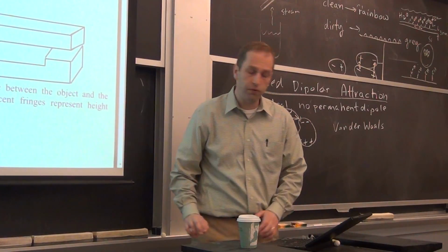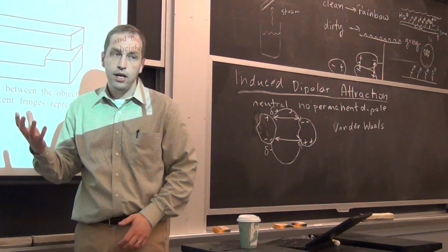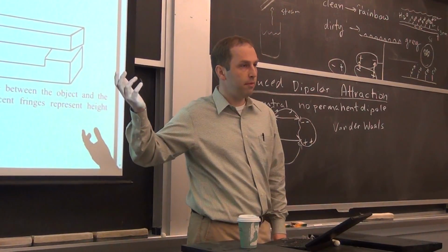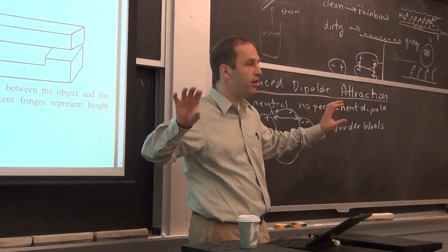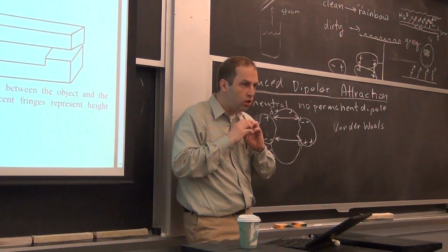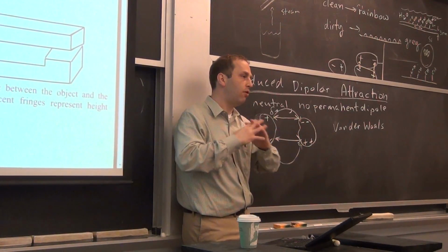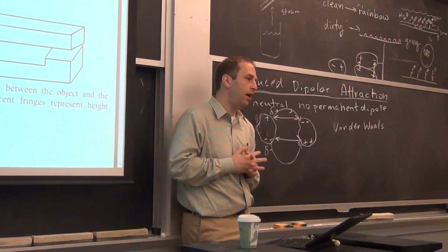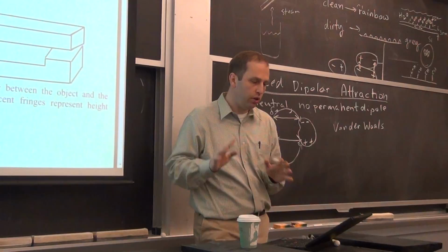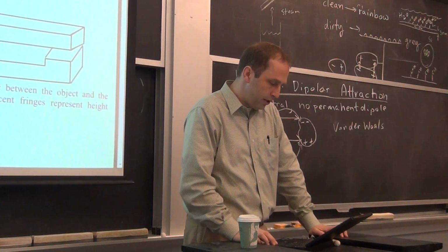What you do have to be careful about is that UV light is also effective at cross-linking organic contaminants. So if you put a thick resist film under it, rather than removing the resist, it would just really toughen it by cross-linking all the carbon in there and creating something that was completely unremovable. So you should only use it with thin layers.